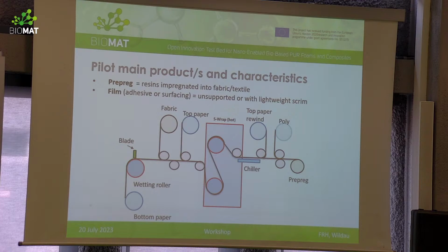So this is a kind of simple schematic of our pilot line. We coat the resin onto the bottom release paper. This then goes underneath a blade, which is set to a certain height, depending on what film thickness you need. And then if you're making prepreg material, the fabric will come down, followed by the top release paper. And then the material goes through a couple of heated rollers. The heat from the rollers allows the viscosity of the resin to drop, which allows it to impregnate through the fabric. And it also stages the resin to achieve a nice level of tack so that the material is nice to handle afterwards. And then at the end of the process, the material is wound onto a roll for easy storage.